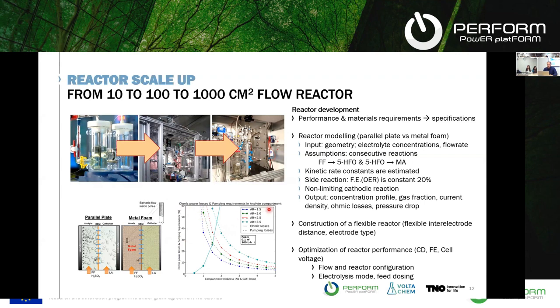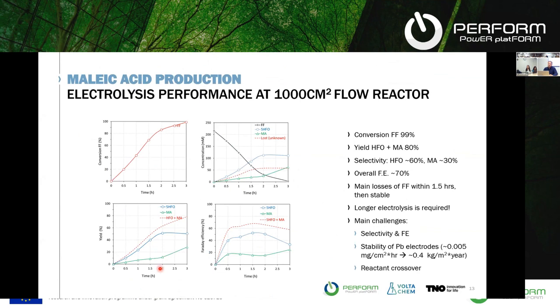With a bit of calculations and experience, we turn to our partner EasyTech to build a 1,000 square centimeter cell that we can use as a preliminary cell to do a proof of concept. And indeed, when we use the cell, we have quite a lot of good results. We have a conversion of furfural that is almost quantitative. We can get about 80% yield of maleic acid plus the intermediate, high selectivity, decent Faraday efficiency.